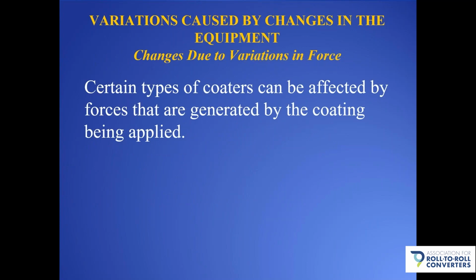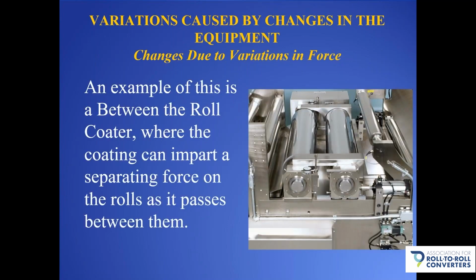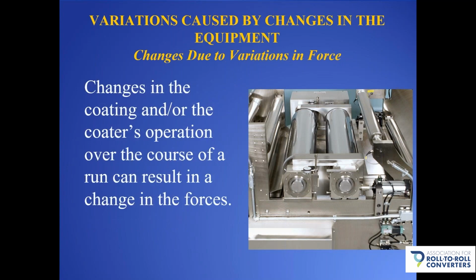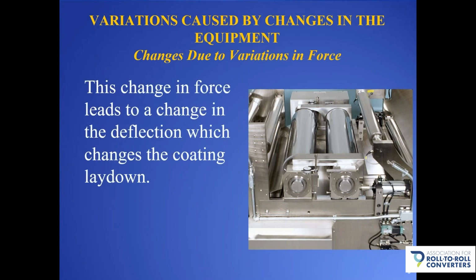Certain types of coaters can be affected by forces that are generated by the coating being applied. An example of this is a between the roll coater, like you see here, where the coating can impart a separating force as it passes between the rolls. So any changes in the coating or the coater's operation over the course of the run can result in a change in these forces, and this change in force will lead to a change in the deflection of the rolls, which will result in a change in the laydown rate.